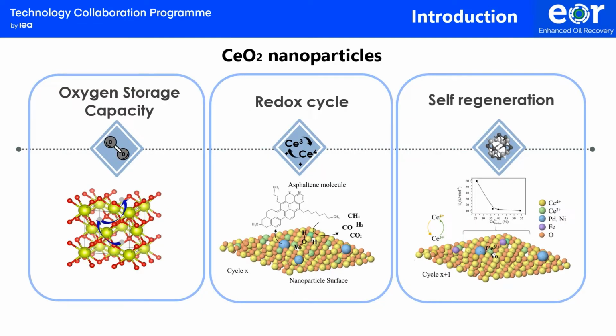With excellent catalytic properties including oxygen storage capacity, highly active redox property, and versatile acid-base chemistry, ceria has been proposed to decompose asphaltene molecules. It was demonstrated that the redox cycle was useful for asphaltene selectivity and conversion over amorphous ceria, and the regenerative capacity of the support allows continuous asphaltene absorption and decomposition without affecting the performance of the material.